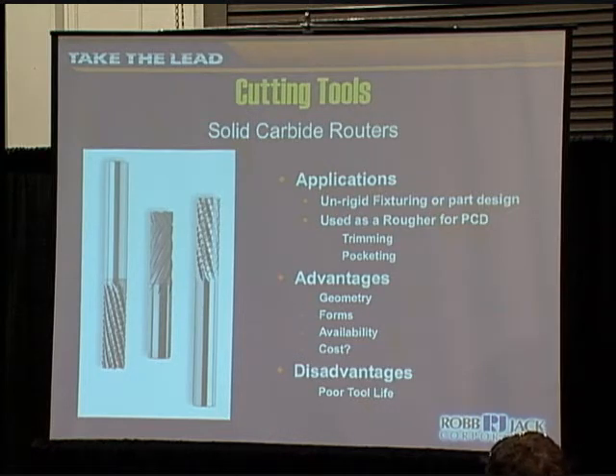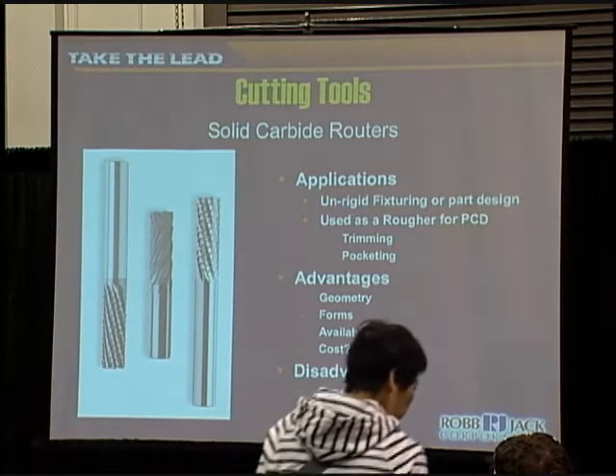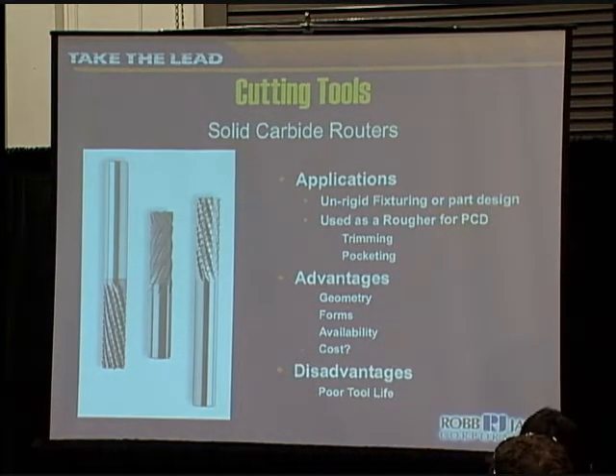You won't be able to hold tolerances very well because you'll get extreme wear on the cutters. You'll have a little bit of difference from the beginning of your part to the end of your part. But it's a really good tool if you have that vibration. So what you could do is rough with the carbide tool and then come back with the PCD very quickly, just to skim up those edges.